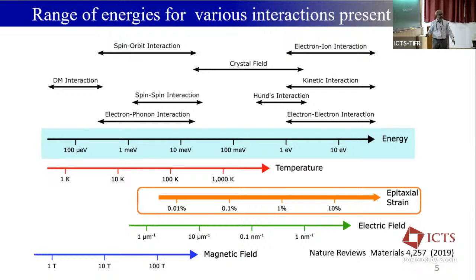So that means there are certain materials, and why I am introducing this is because this SrIrO3, which I will talk about, is very difficult to stabilize in the bulk form because it requires very high pressure and high temperature synthesis. But by making thin films, by introducing strain, you can stabilize this SrIrO3 in a perovskite phase, which is a very potential candidate material to realize topological electron transport. So this epitaxial strain and the spin orbit interaction, these are the two energy scales which are very important in the context of this work.